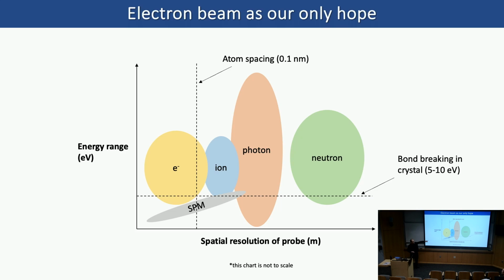And the reason why this is so important is because we learned that from SPM. If an atom doesn't have the bond to stabilize the structure, they will simply evaporate at room temperature. So you no longer get a stable atomic structure there. You would need a technique that has the capability of breaking bonds and forming a crystal so that the whole idea of atomic engineering could work.